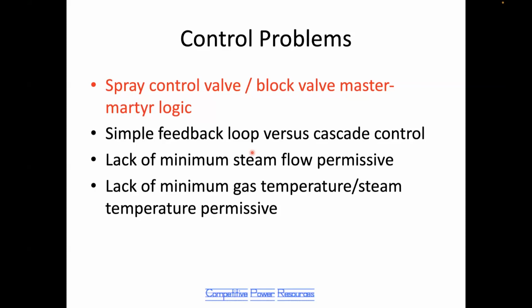I already mentioned that the simple feedback loop for control does not work well on most HRSGs, so a cascade control system is necessary. The Attemperator should also have a minimum steam flow permissive. The Attemperator cannot possibly work if there's not enough steam flow to carry the water droplets downstream and evaporate them. So it's generally around 25% of rated steam flow before you should allow the Attemperator to come into service.